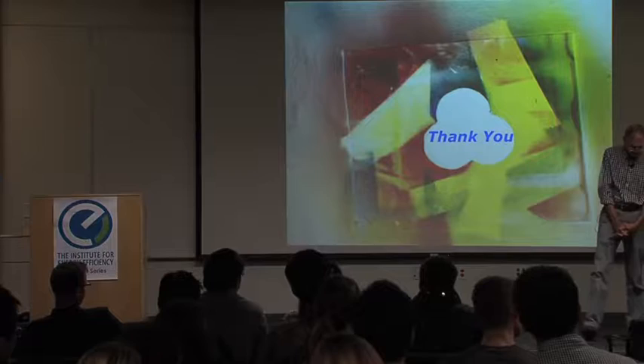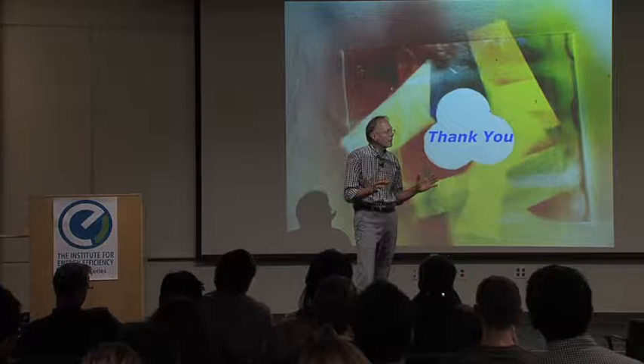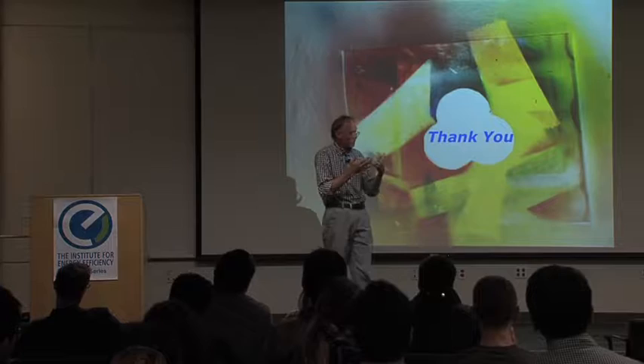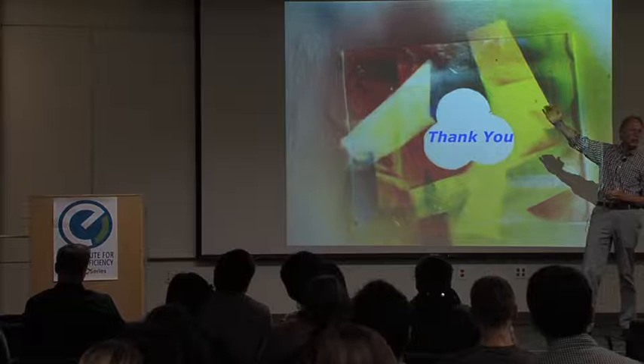A little hand waving now, right? But the gist in general is that when we use a ProDOT, we have substituents pointing above and below the ring, at a tetrahedral carbon where we substitute. That means those chains don't easily pack as they do in, say, a PEDOT. And so when you go into the fully oxidized form, that long wavelength tail is pushed into the infrared. It doesn't swing back into the visible nearly as much.